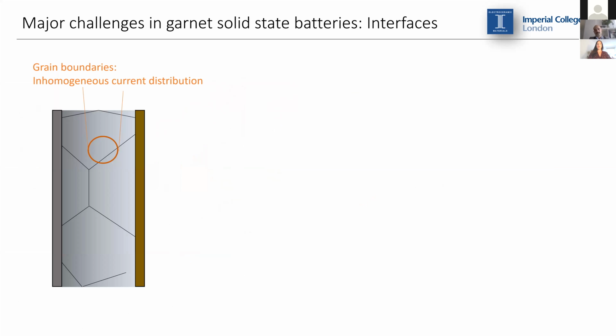So what are the major challenges in developing garnet-based solid-state batteries? All of them are focused on the interfaces. On one hand, we have the grain boundary interfaces. We are working with ceramic materials that are polycrystalline, and therefore we can create a lot of inhomogeneities chemically in the grain boundaries that can induce very different lithium mobilities and inhomogeneous current distribution.